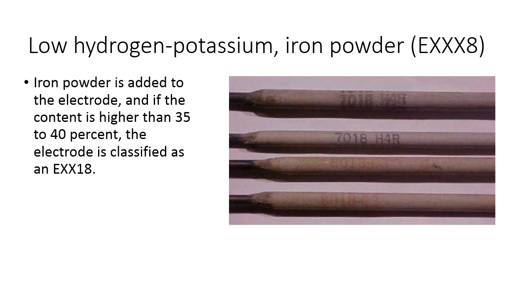Here we have a picture of some typical low hydrogen electrodes. Iron powder is added to the electrode, and if the content is higher than 35 to 40%, the electrode is classified as EXX18. I picked that one out of a military manual, so that's where I got that information. But you can see here some examples of E7018, which is a low hydrogen potassium iron powder covered electrode. And they make them in E8018s and 9018s. When they do that, they just modify the chemistry of the core wire, and then they throw some additional alloying elements into the flux coating to get it to the chemistry that you want.